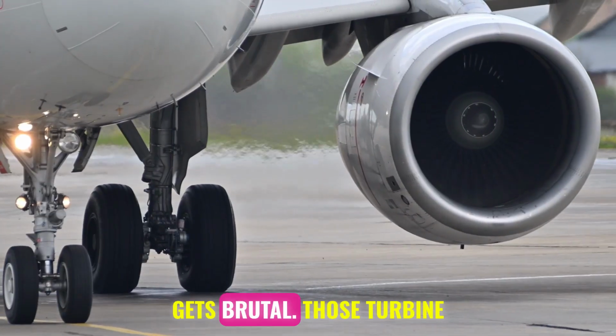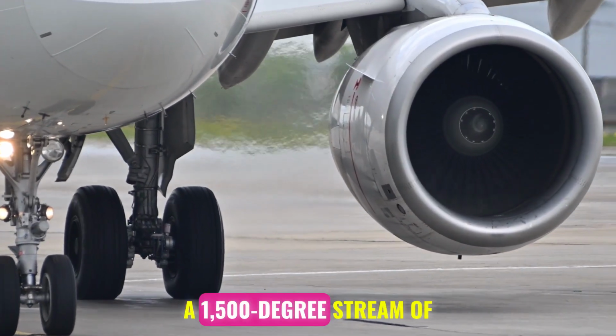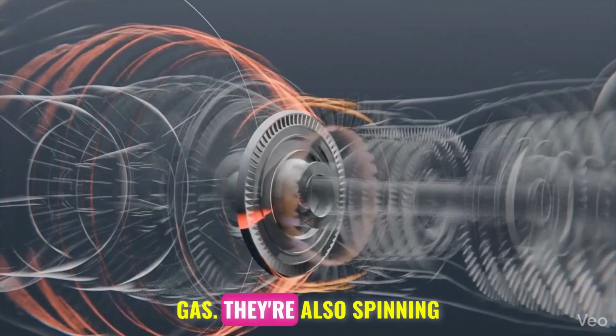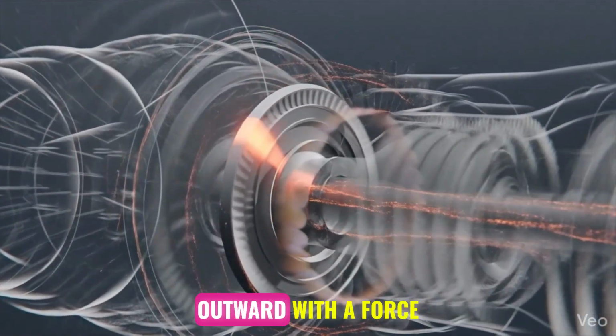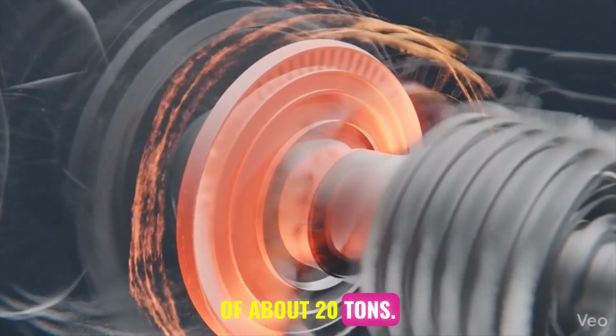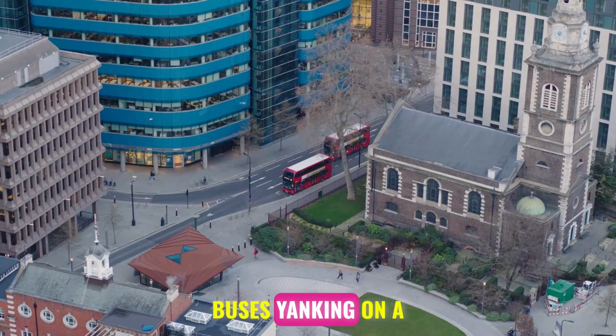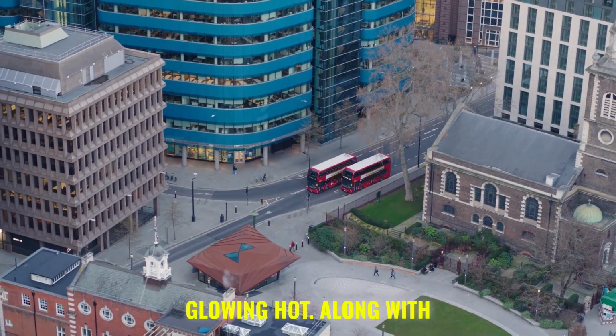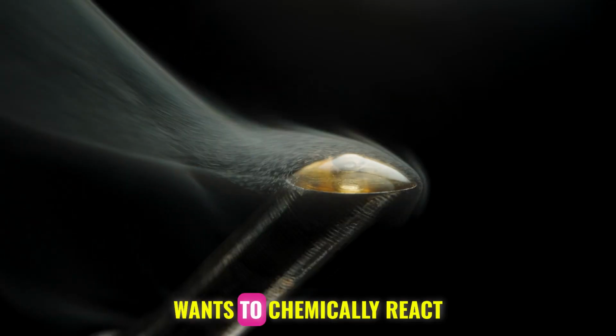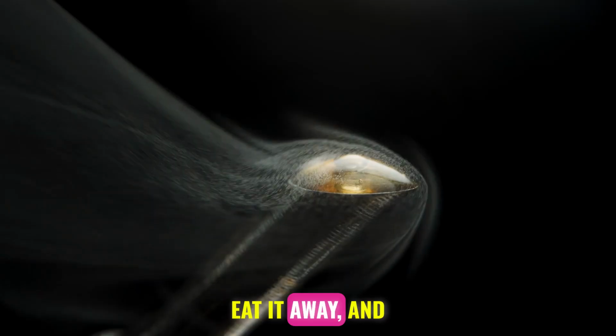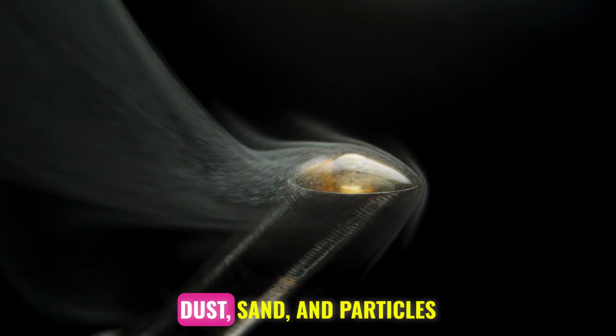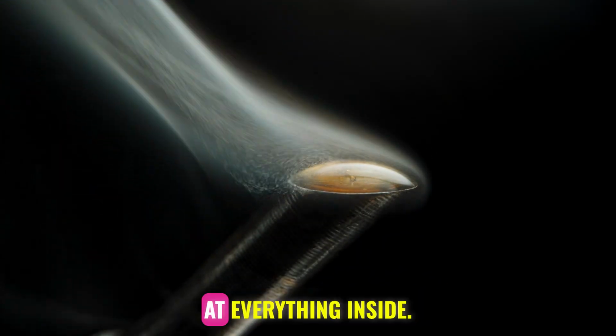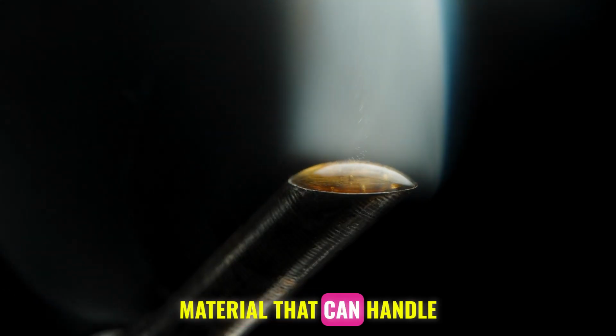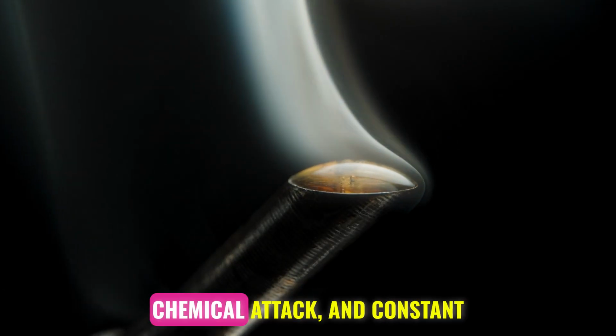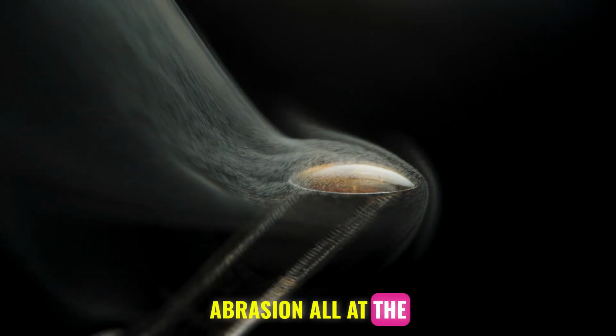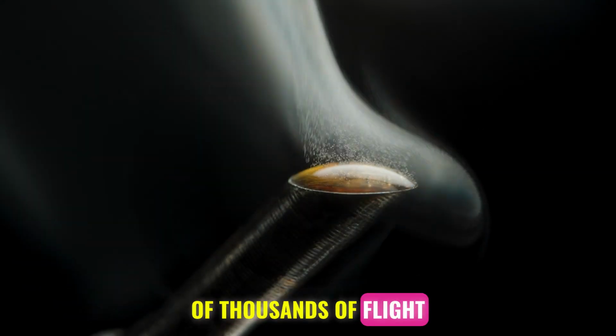Now here's where it gets brutal. Those turbine blades are sitting in a 1,500 degree stream of gas. They're also spinning so fast that each blade is being pulled outward with a force equal to the weight of about 20 tons. That's like two double-decker buses yanking on a single blade while it's glowing hot. Along with that, the hot oxygen wants to chemically react with the metal and eat it away, and the air being sucked in from outside carries dust, sand, and particles that slowly grind away at everything inside. So you need a material that can handle insane heat, enormous stress, chemical attack, and constant abrasion, all at the same time, for tens of thousands of flight hours.